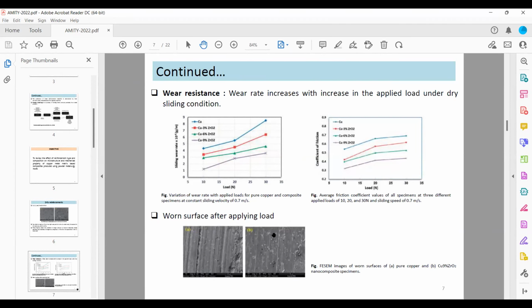Accordingly, the worn surface analysis shows that when only copper was used, there is ploughing of material, delaminations, and grooves are present. But when ZrO2 is added, as ZrO2 offers a lubricating effect, there is a smooth surface finish.